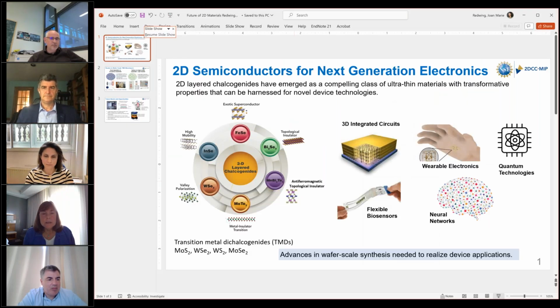And then in addition to the reactor specific needs, there's also needs to understand defects in these materials. So even though they're single crystal, there's still a lot of defects. There are voids, there are grain boundaries, there are point defects like chalcogen vacancies. And also you can have regions that have multi-layers on them, so bilayers or multi-layers on a monolayer film. So there are needs there in order to develop techniques where we can characterize defects on wafer scale films, and of course correlate defects with device performance, and then ultimately eliminate the defects.